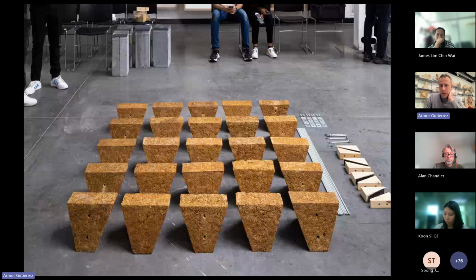So we replicated the system using Sugarcrete, bound with silica binders. One of the main challenges that we had is that we needed to achieve a compressive strength that was higher than what we had at the time. We calculated with the engineers from AKT II that we will need to reach 5 megapascals of compressive strength, and we were down at 1 at the time. So we worked with colleagues in the Sustainability Research Institute, material scientists, to find new binders and to find new compositions that could achieve that compressive strength that was required.